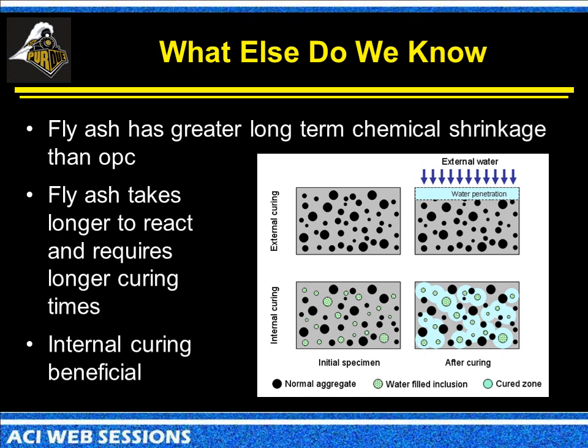So the idea behind the internal curing is to replace some of the solid particles here, which would represent sand or our aggregate, and replace those with water-filled inclusions. Those water-filled inclusions can be a variety of things. It could be a polymer that's filled with water. It could be a cellulose fiber that's filled with water. It could be lightweight aggregate particles, lightweight aggregate fines that are filled with water. The benefit of this is these water-filled particles will hold onto the water, and they'll actually absorb a little bit of water from the mix while it's mixed and while it's placed.